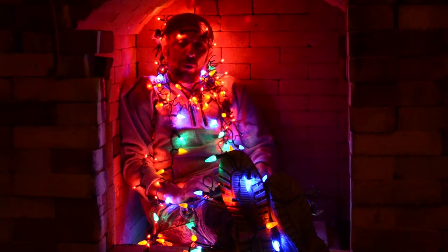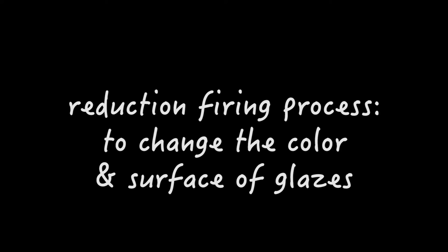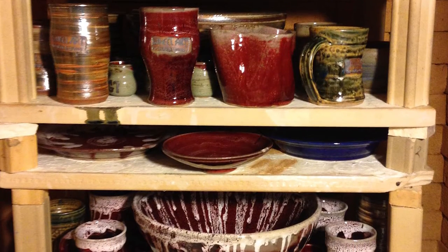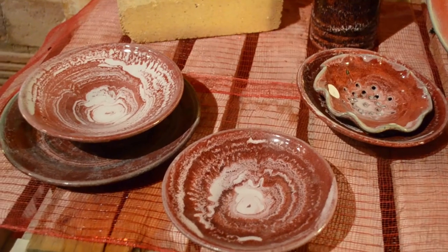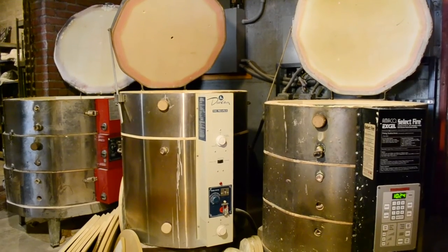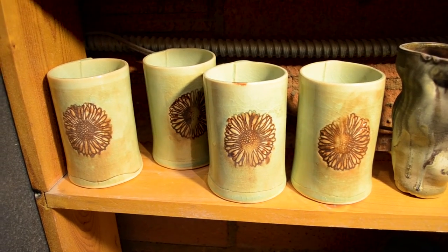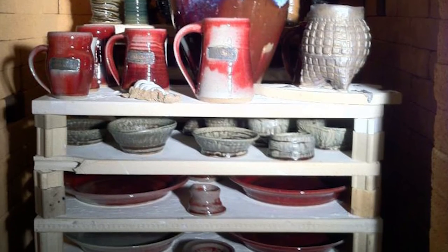All of the pots have been fired. It's often said in a pottery studio that opening the kiln is like Christmas every time — you never know if the present will be good or bad, but it is definitely a surprise. The process of reduction firing, to reiterate, is to change the color and surface of glazes. One of the glazes I use is referred to as a copper red glaze. These are traditional Chinese glazes that only turn red under good reduction of oxygen levels within the kiln atmosphere. These glazes turn different variances of red depending on the chemistry and reduction levels during the firing. In electric kilns with oxidation, this red glaze actually turns a minty green. But whenever you fire in a gas kiln and reduce oxygen during certain parts of the firing, those glazes, if everything goes well, will turn red.